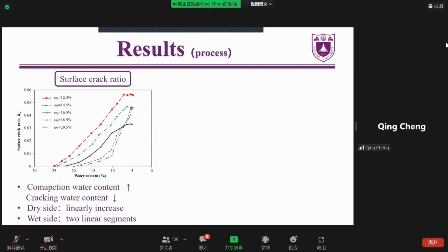Then I will show you some quantitative results, and this figure shows the change of the surface crack ratio with water content during drying. It can be found that the cracking water content, which means the water content when the first crack initiates, of the samples compacted on the dry side and at the optimum water content is higher than those of the samples compacted on the wet side.